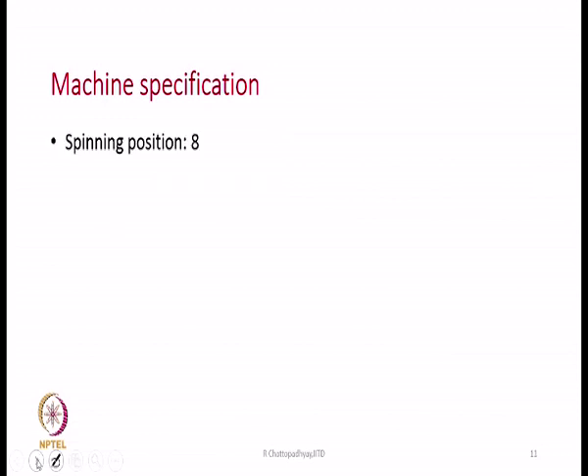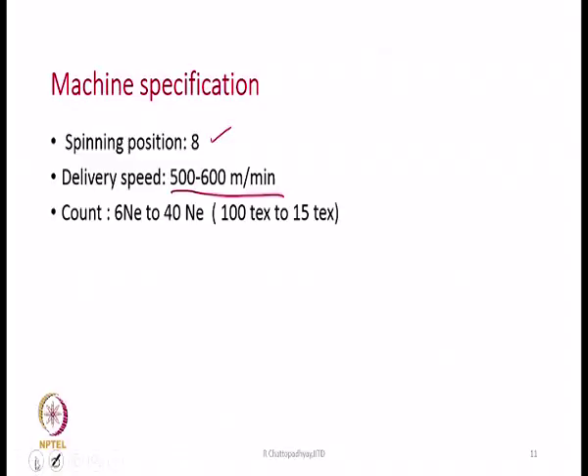Machine specification that we have is spinning position is 8, whatever commercial machine is available. Delivery speed is very high, 500 to 600 meters per minute. We have not seen other technologies having this kind of speed. Even vortex spinning has a speed at the most 500. That is what the machine manufacturers claim. Commercially, it may run at 350 meters per minute or maybe 400 meters per minute. Delivery speed here is quite high. Count that can be spun varies from 6 Ne to 40 Ne, or that is 100 tex to 15 tex on the finer side.